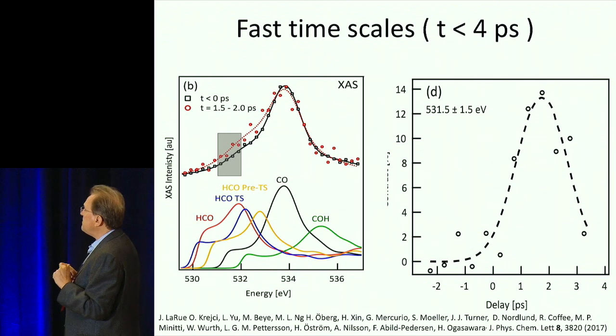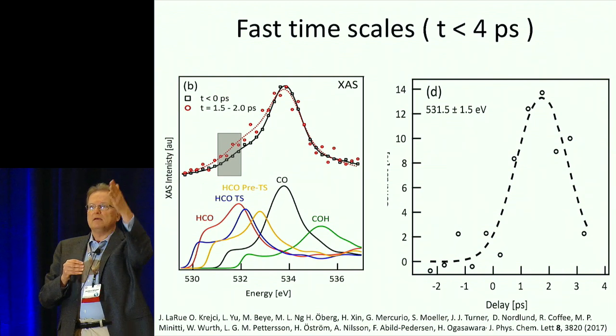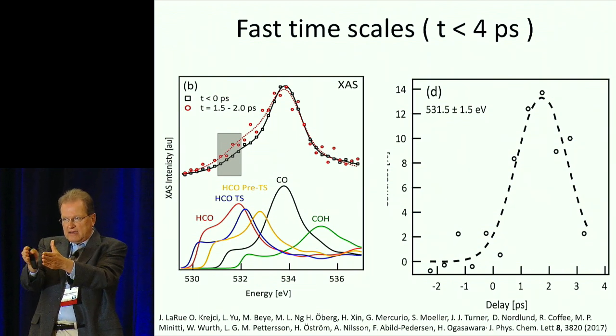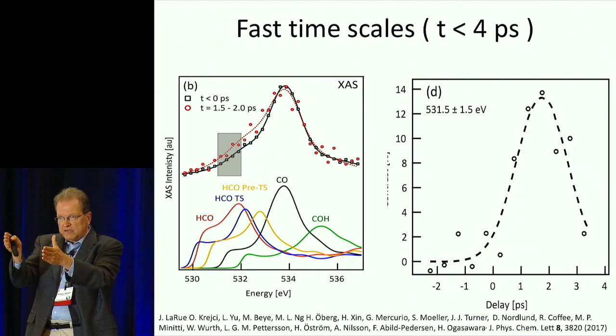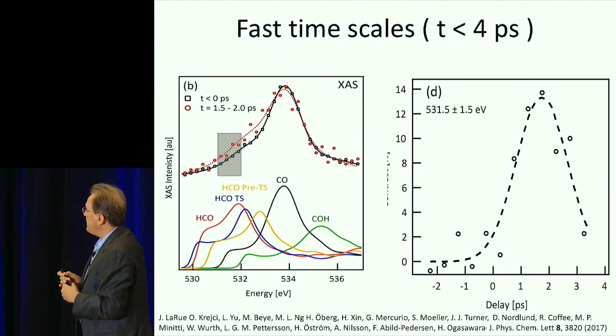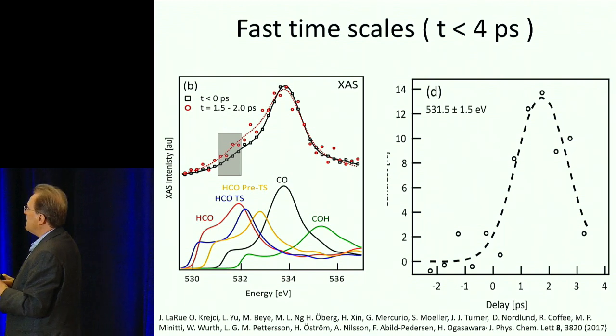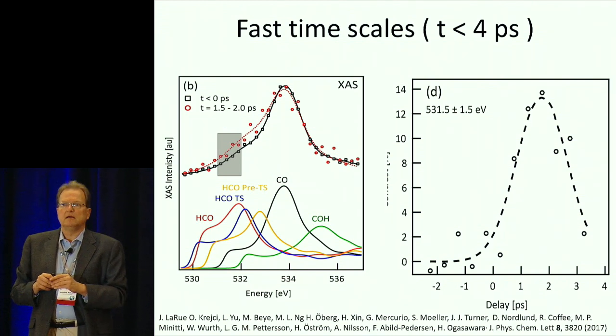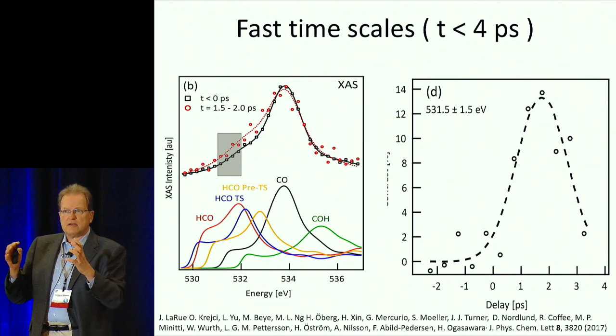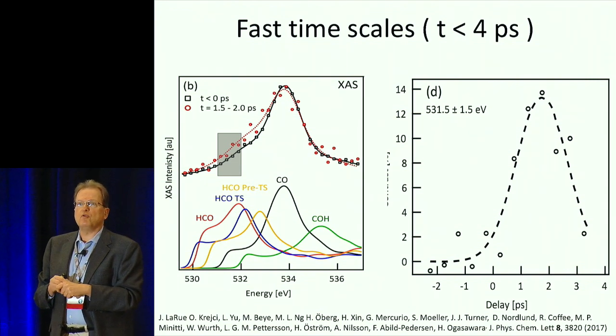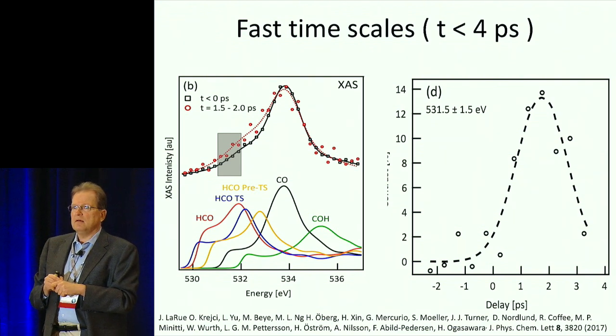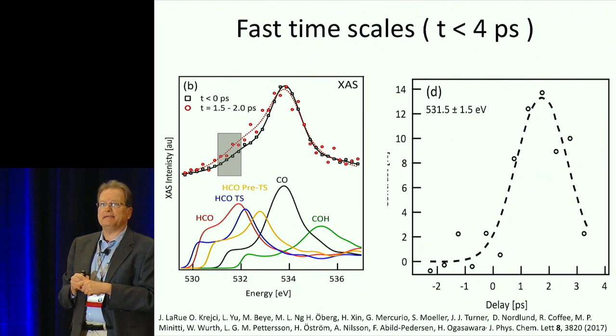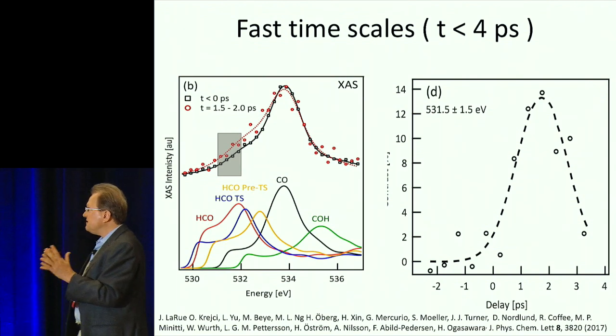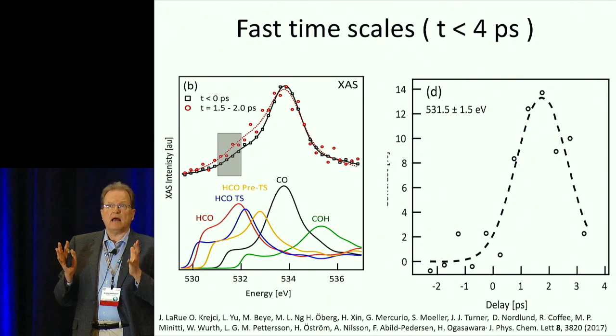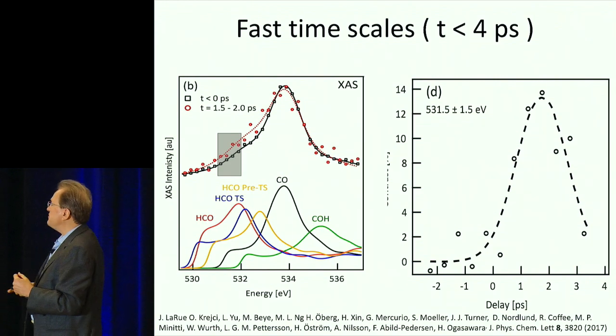Then we can look at how the time evolution of this looks by looking at the intensity as we delay between the optical laser and the X-ray laser. We are delaying the time as we are looking at the species after we pumped it. And as you can see, this actually peaks at around 1.5 picoseconds. So obviously the CO and the hydrogen are running into each other and forming these HCO species, but it's not stable. Actually, it will decay. So it tells us that this intermediate is only metastable. And we are also seeing species on the way to the transition state.